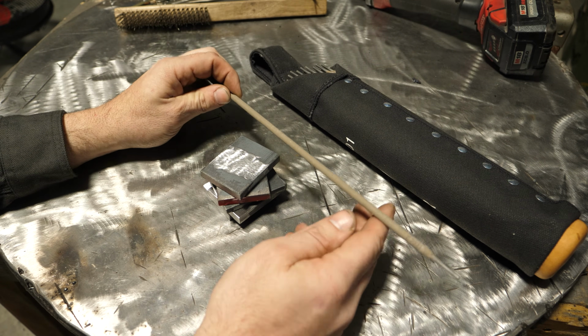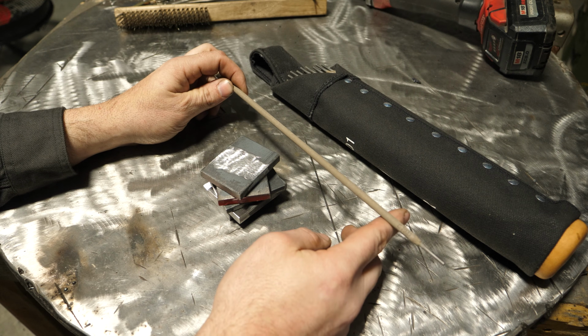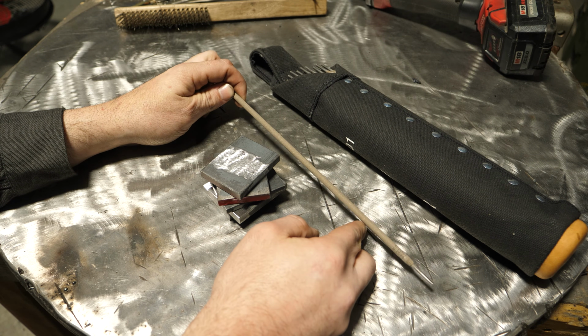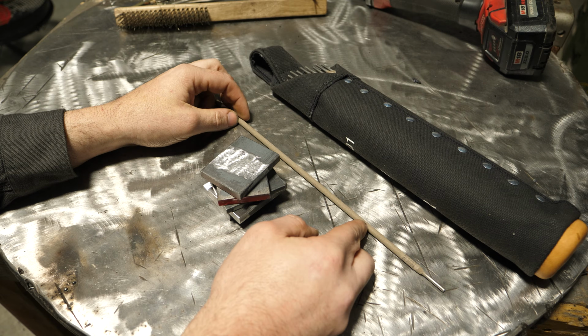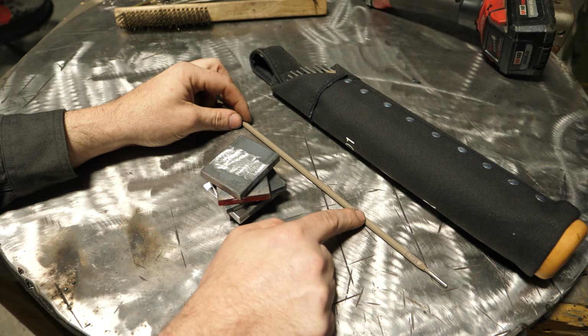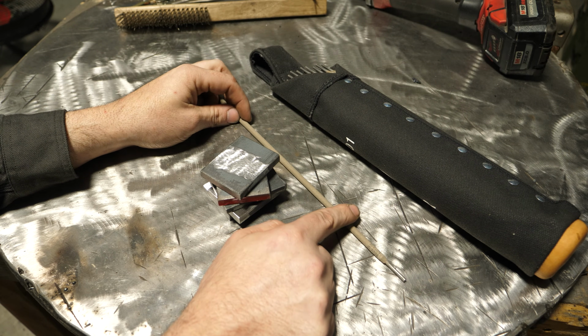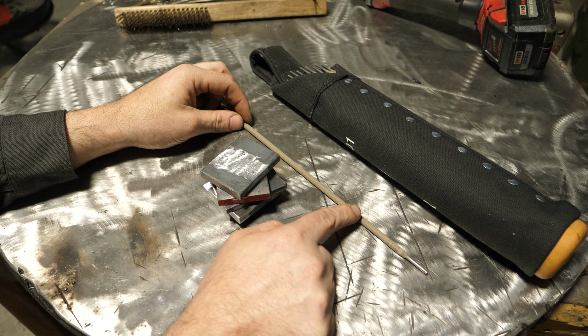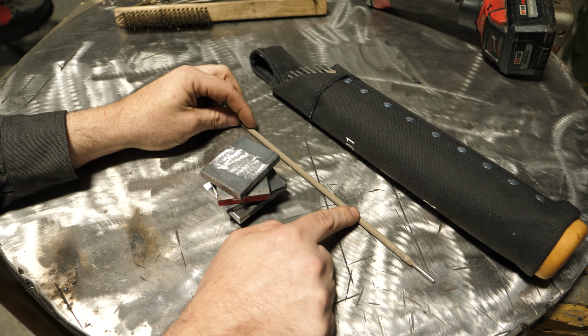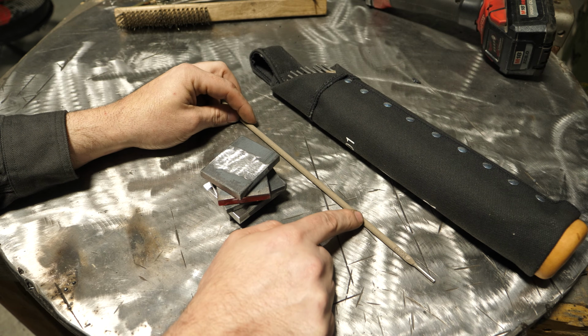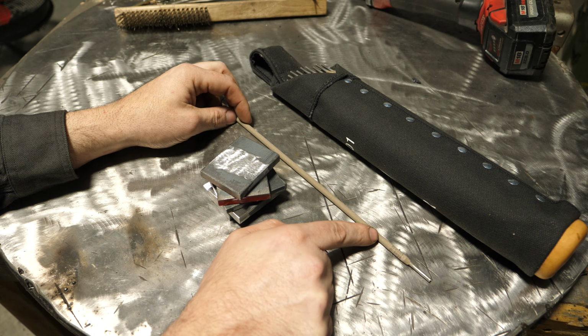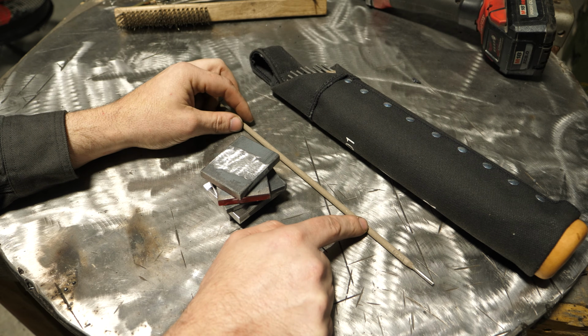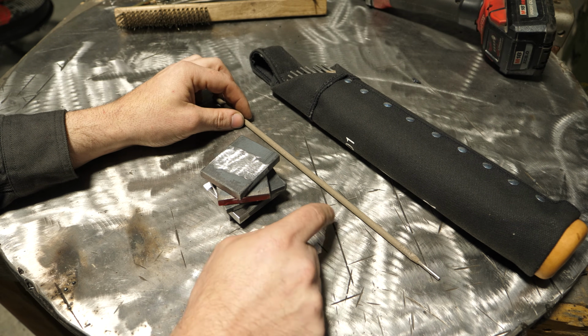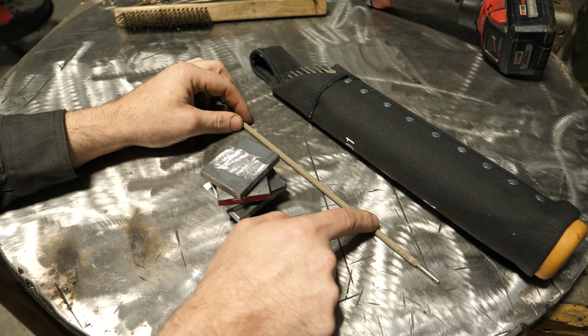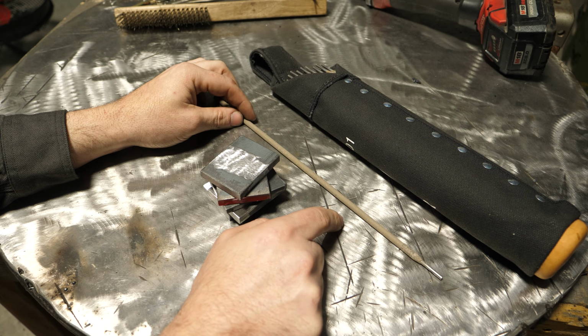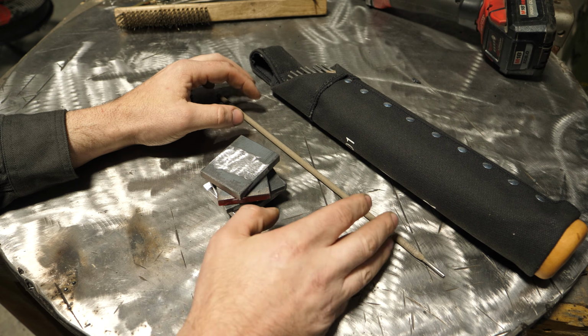Now, this is not a low hydrogen rod. Therefore, this is not code legal to use on anything that specifies low hydrogen, and you would not want to weld high strength steel with this. So any kind of AR500, AR400, or stuff you might find on a tractor that's wear resistant, and even in theory, really thick steel may be susceptible to hydrogen embrittlement. And I'll put a video link down in the description if you want to learn more about that, but you don't want to run this rod for that. So non-critical work is a good overview of that.